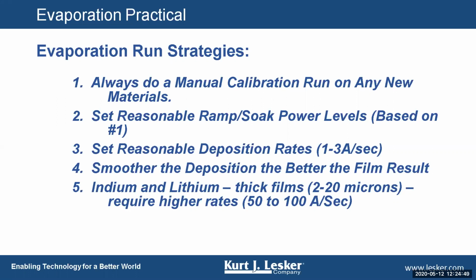Number one is always do a manual calibration run on any new material. If you're evaporating a material for the first time, I am always cautious. I put it in a boat. I start to run up the power manually. I see how the material interacts with the boat. I make sure that there are no compatibility issues. I'll slowly ramp the power up on the source until I get a decent evaporation rate coming off of the material, and I will record the power that I get the evaporation rate at. So that's a very important thing to do. It's a very important thing to note.